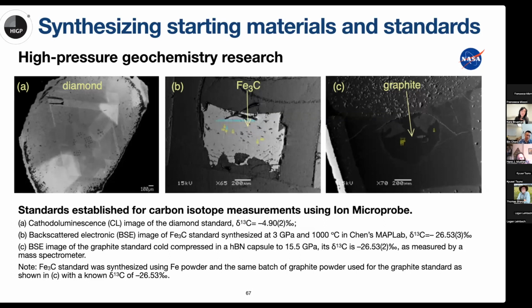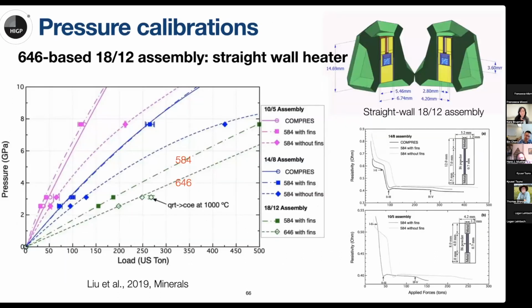Oh yes, in one of the figures, particularly for viscosity, I showed that before the structure transition, the viscosity of iron carbon and iron or iron sulfur alloys are pretty similar. So they are at least at the same level. But we found that after the structure transition at 5 gigapascal, the viscosity of iron nickel carbon would increase, would be higher, like a factor of 2 to 3 higher than that of iron sulfur and liquid iron.